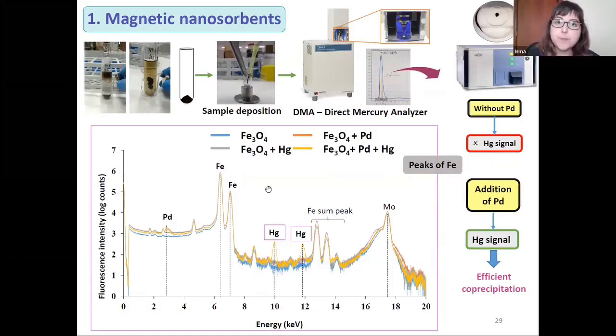of this slide. A new or further research of magnetite derived from the previous one consisted of the use of noble metals, palladium, silver, and gold in presence of these precursors of magnetite, iron 2 and iron 3, and also in presence of mercury as analyte. We can see that in that case, palladium shows the better extraction, allowing the efficient trapping of mercury into this magnetite. In this work, we use the direct mercury analyzer to perform the study of this procedure.